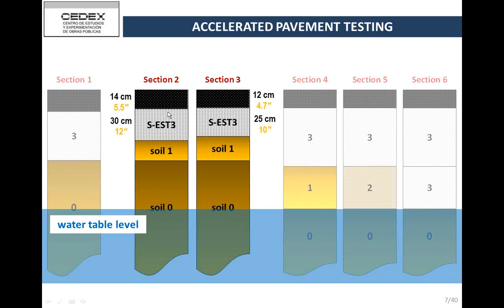So section 2 has a thickness of 30 centimeters for this material. This is the typical thickness that we use in Spain. And section 3 has 25 centimeters, which is slightly below the first value. So we wanted to see the performance of these two sections, and the difference in performance between section 2 and section 3. I should say that these two sections were supposed to have 12 centimeters of asphalt, but in practice section 2 also had a thicker asphalt layer.